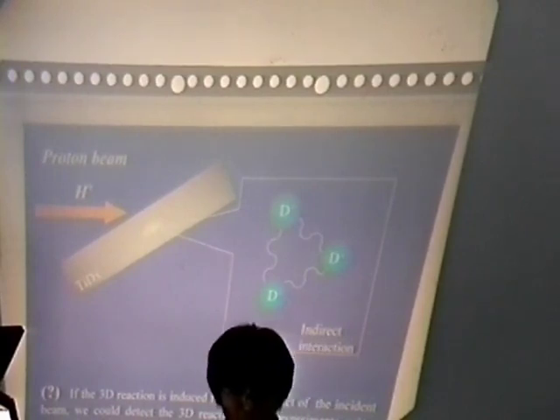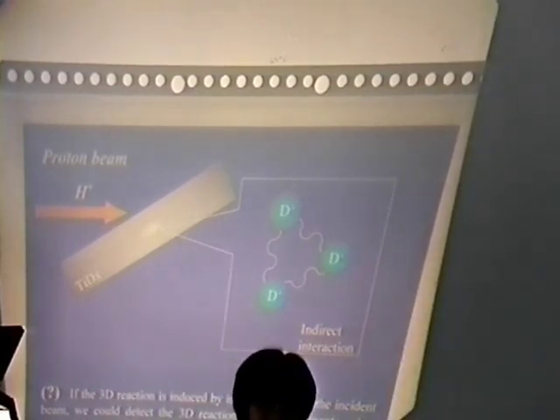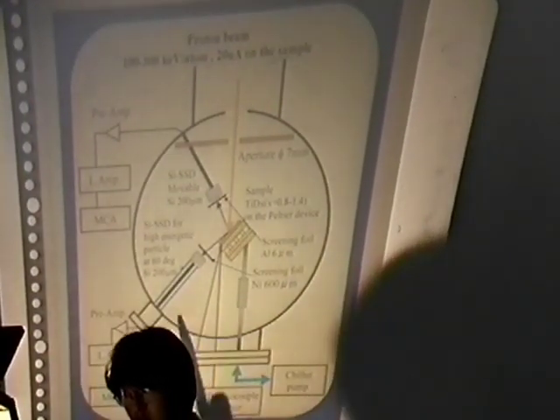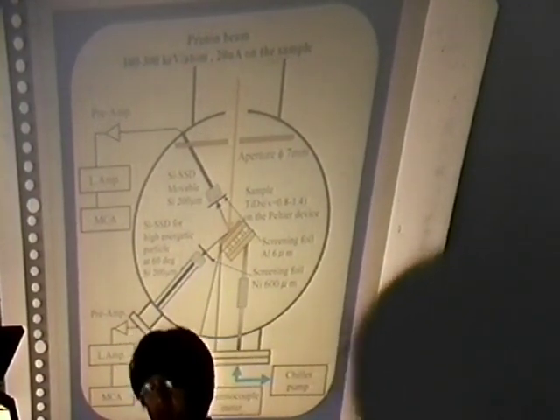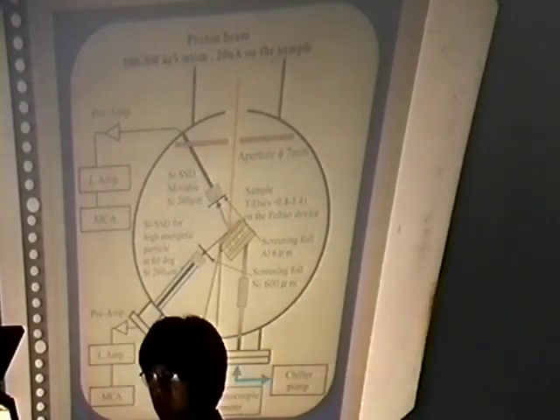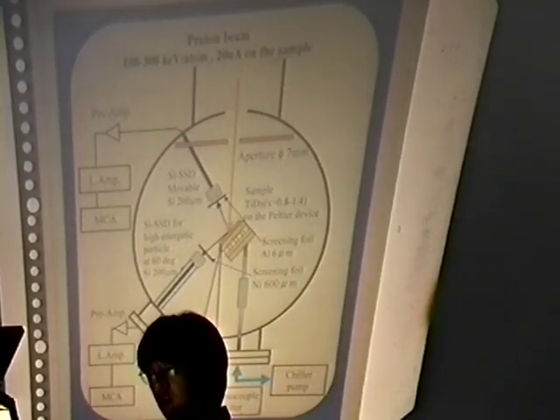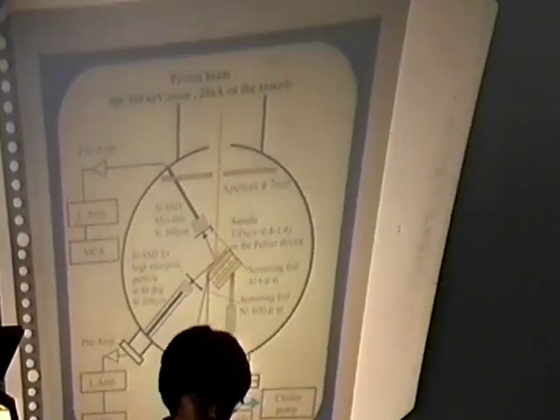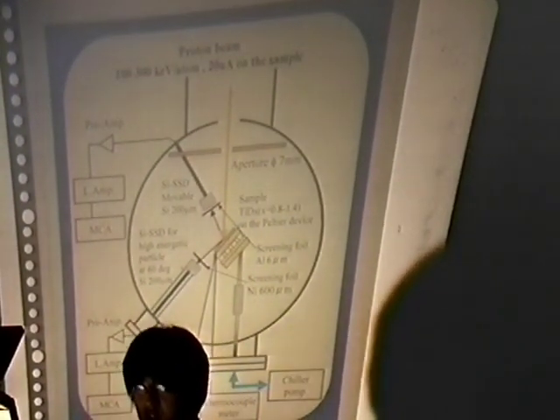And to confirm that the 3D reaction is an indirect reaction, we perform the experiment using proton beam instead of deuteron beam. If our assumption previously mentioned is true, we could detect the 3D reaction also in the experiments using proton beam and TIDX. The setup is similar to the deuteron beam experiment, but this is a detector for high energy charged particles measurement. So screen foil of nickel 600 micron was set in front of the detectors. And we call this detector EH detector.